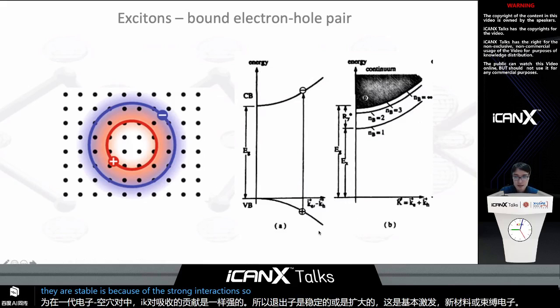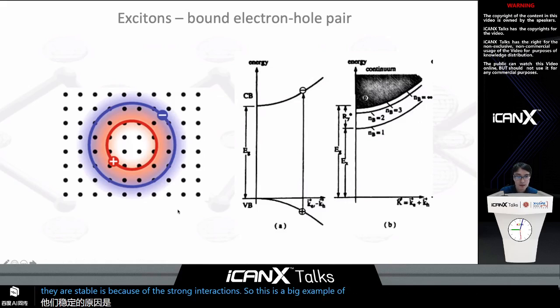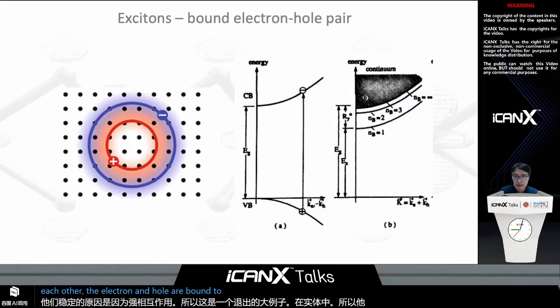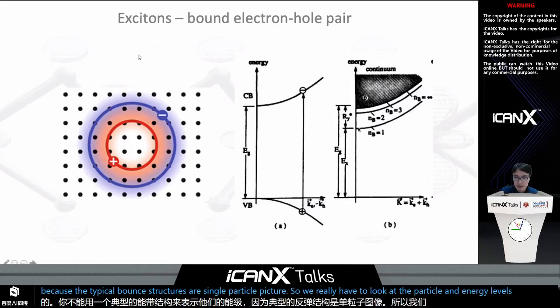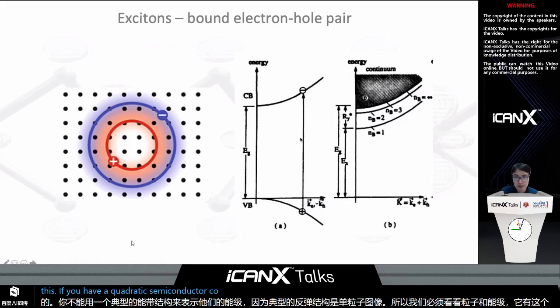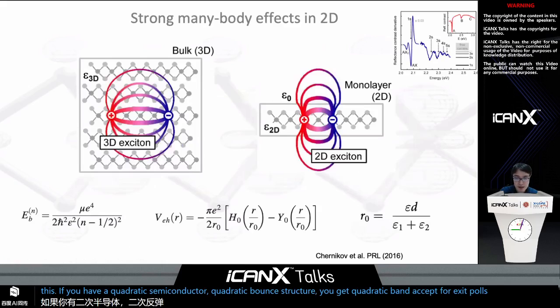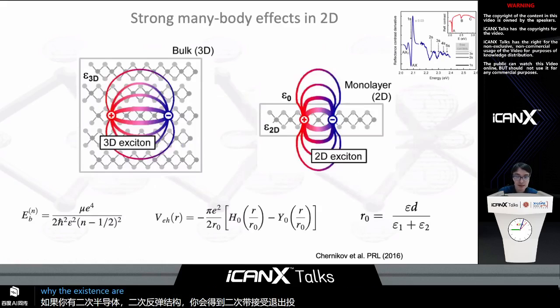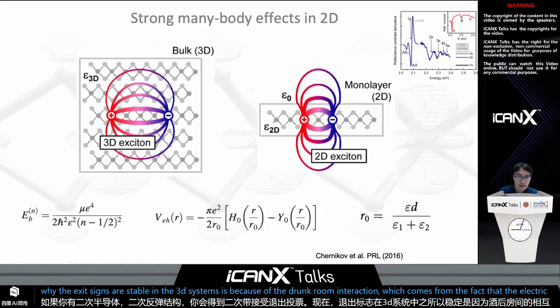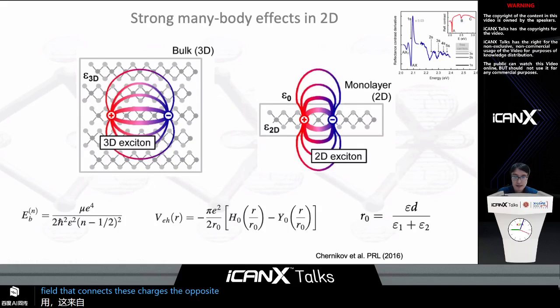So this is a typical example of an exciton in a solid. The electron and hole are bound to each other, and you cannot really represent their energy levels in a typical band structure, because typical band structures are a single particle picture. So we really have to look at the two-particle energy levels. If you have a quadratic band structure in the semiconductor, you get a quadratic band for excitons. Now, the reason why excitons are stable in 2D systems is the strong Coulomb interaction, which comes from the fact that the electric field that connects these opposite charges can go around outside the two-dimensional solid.